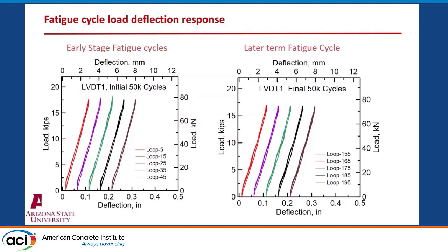One of the analyses that we have to do is to look at the fatigue results. We look at every 50,000 cycles, collect the data for 100 cycles, and then look at the loading and unloading. That response is used to calculate the stiffness. The question is, how much stiffness do I lose with significant cycles of fatigue? Each loop represents 50,000 cycles, as we go through these different loops, from the initial 50,000 cycles to the final 50K cycles.